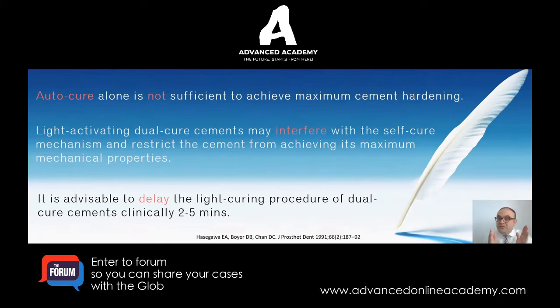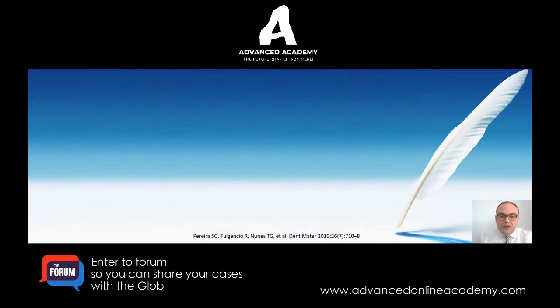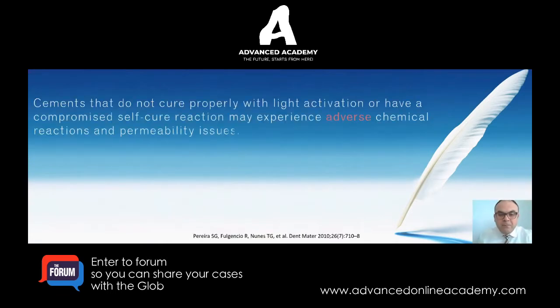Between 2 to 5 minutes is the optimum time for an adhesive or a self-adhesive cement before hitting it with the curing light. Less than 2 minutes, don't; more than 5 minutes, don't hit it with the curing light. That's when you get the best bond strength, because you give a chance for the chemical cure to work and also for the light cure component to work as well. Cements that do not cure properly will have an adverse chemical reaction and permeability issues.